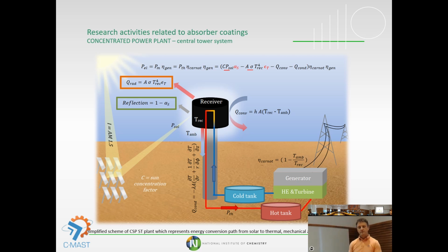So people quite often describe that the surface has a much higher temperature than inside, or the opposite, just because the heat transfer is decreasing with time, and just because some, let's say, oxide layer is growing below. And then, as I said, you run the turbine at the bottom quite often in order to produce electricity 24 hours. There should be a really enormous storage tank with molten salt. Imagine, I don't know, 30,000 tons of molten salt at 320, 350 degrees in order to fulfill the demands of the generator during 24 hours.